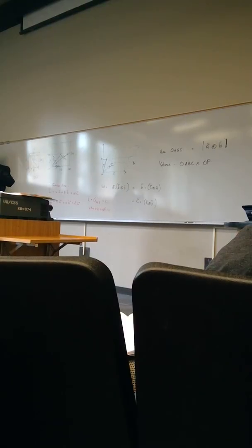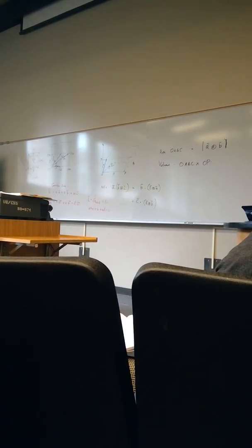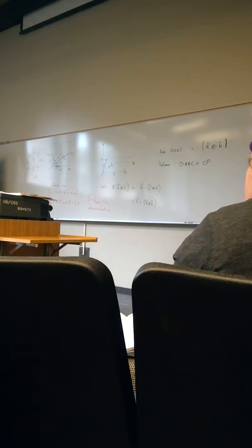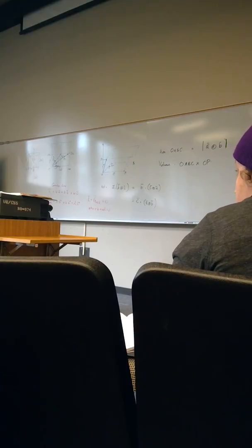All I'm saying is that you have some interatomic spacing, a whole family of planes, and you have a sense of that magnitude. You also have a sense of the normal to the set of planes. So you take the magnitude of the interatomic spacing, take the inverse of that, and that gives you the magnitude of the vector. You keep the same direction, just the normal. You plot that vector, with magnitude as the reciprocal of the distance, and the direction given by the normal to the set of planes. So conceptually, that is the concept.